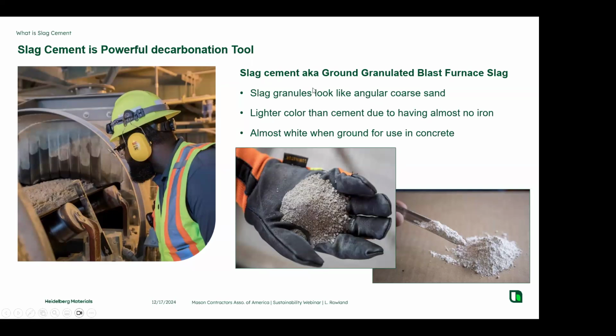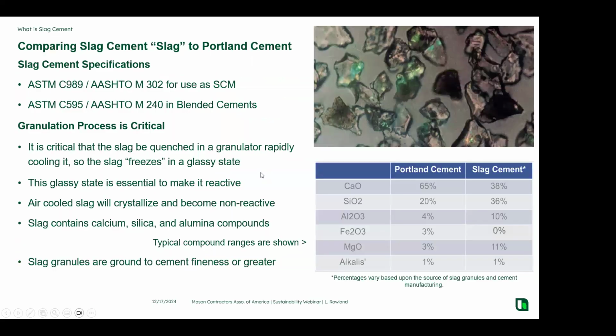So the process is to take those granules that look essentially like a coarse sand, run them through a cement mill or a grinding mill, a finish mill, we typically call those, to make something that is as fine or a little bit finer than Portland cement. It's very important that these materials meet the specifications, the ASTM C989, which is for slag cements used as a supplementary cementitious material, and they can also be used as a blended cement. I mentioned earlier our type 1S40 cement that meets this ASTM C595 spec.